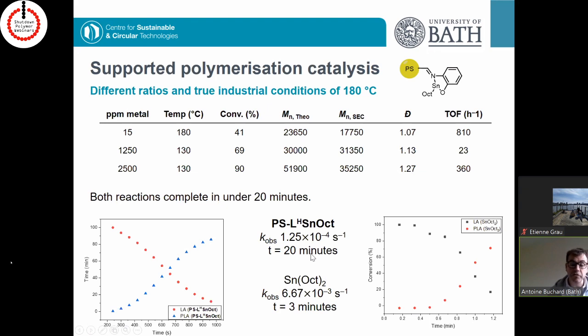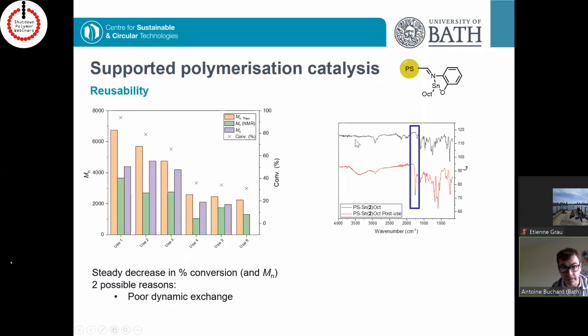But in our case, we've got something that happened in 20 minutes, which is not bad, and it is quite well controlled as well, with really decent dispersities and a good control of the molecular weights. If you look at what we expect, depending on how much initiator you've put in the first place, and what you get, let's say, by SEC. Something quite attractive